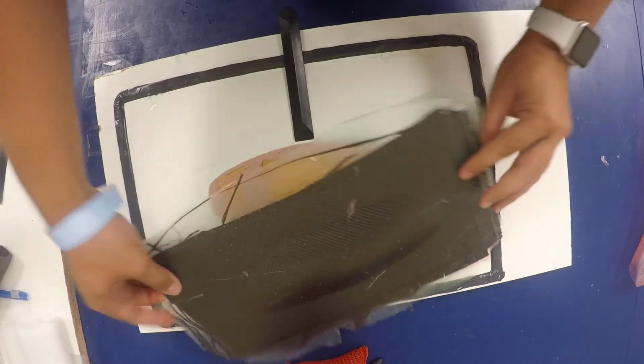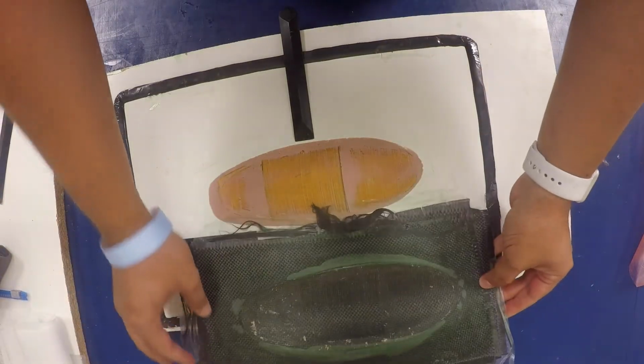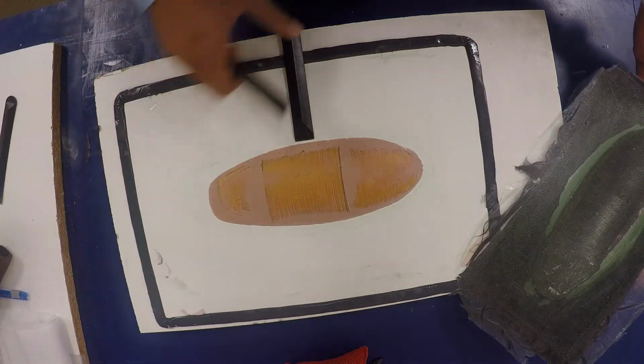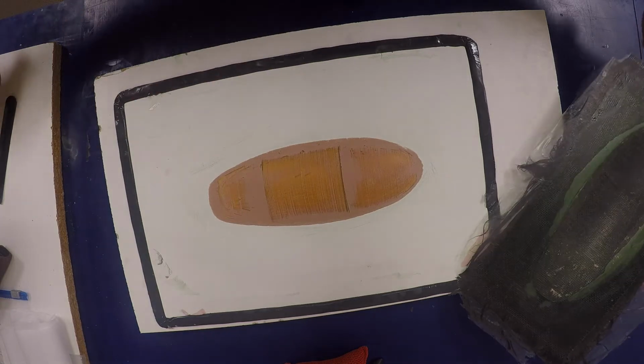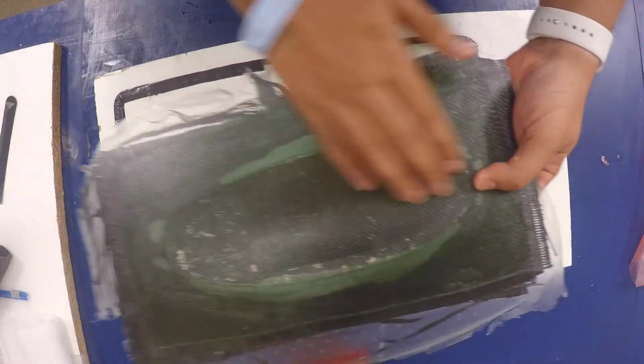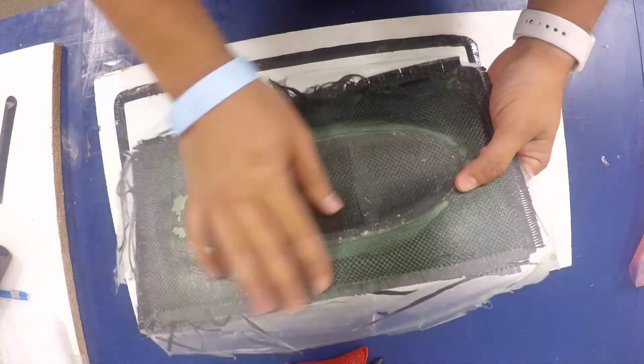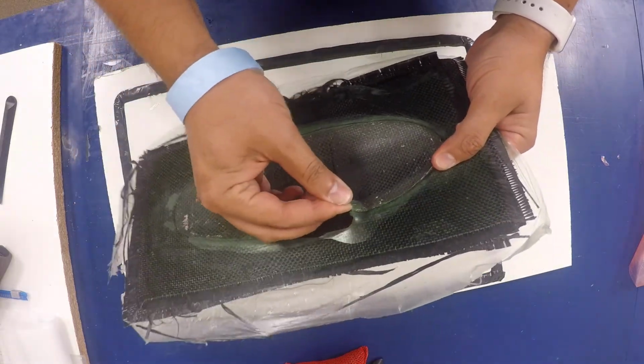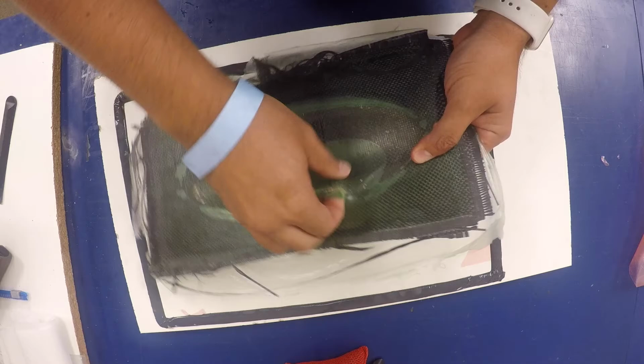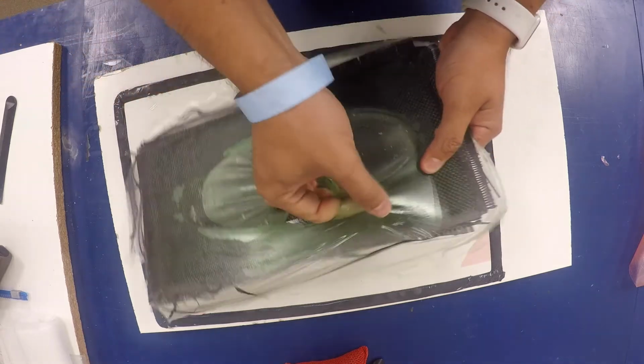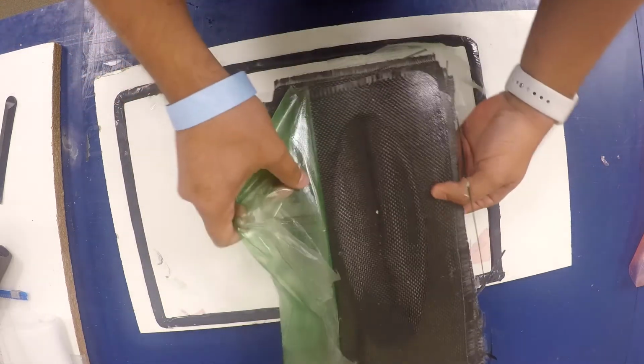In this example, the mold was waxed before the PVA layer was applied. You can see the layer of PVA that separated the wet carbon fiber and the wax on the mold as the part cured. If you use PVA and you can't peel it off as shown here, you can also remove it by rubbing a wet paper towel against your final product or your mold to dissolve it.